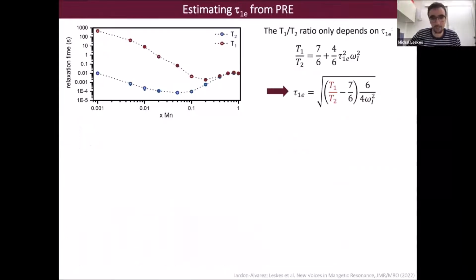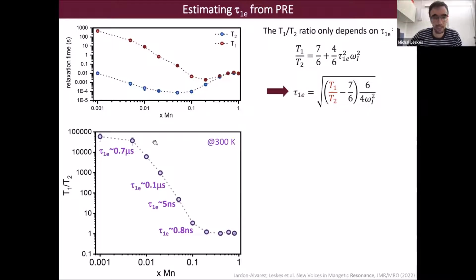Okay, so we can take this even a step further, and using the equation I presented before, we can try to estimate electron fluctuation rates or times. And so just by plugging in the values here for T1 over T2, we are able to get electron relaxation times, which are in the order of 1 microsecond at this very low concentration. And as we increase the concentration, they rapidly decrease below 1 nanosecond. And it would be nice to validate this type of measurement.